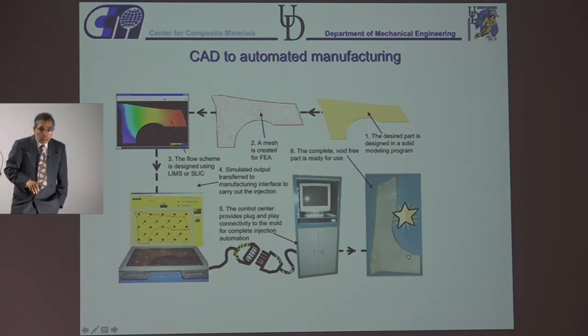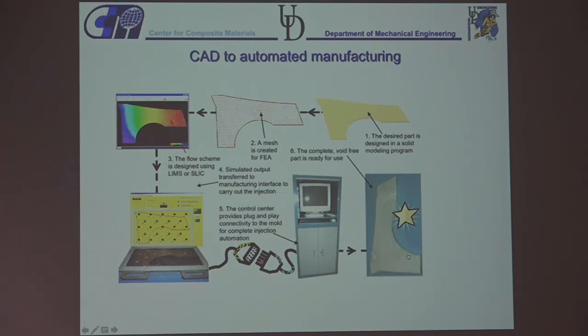Can you predict also the fiber disorientation during the process? The disorientation of what? Okay, so in this process, usually you have a fabric and the fibers are continuous, and they usually don't change orientation. It's the resin that's flowing in between the fibers. But in high pressure RTM now, there is an issue of fiber washout. The pressure is so high that you could actually have some fibers that move aside, and they can create larger defects like gaps, which is what you're referring to. Those gaps can be detrimental for your mechanical properties because that's a real defect then.